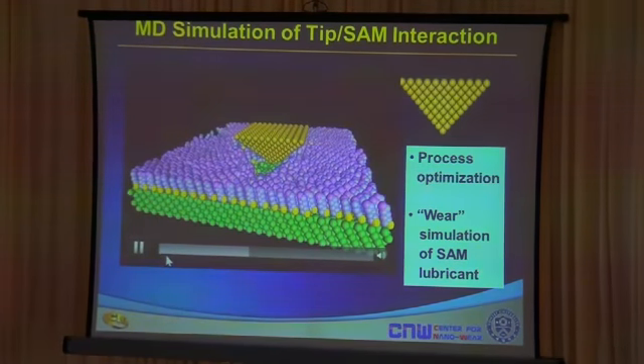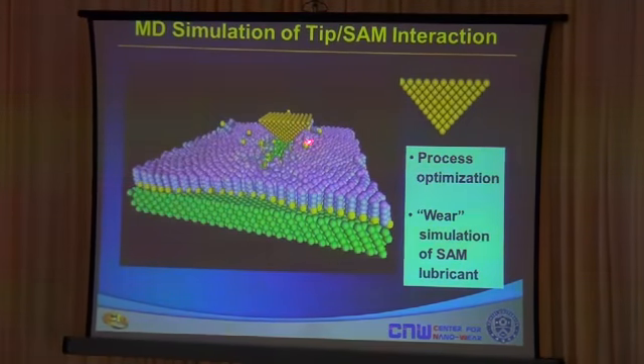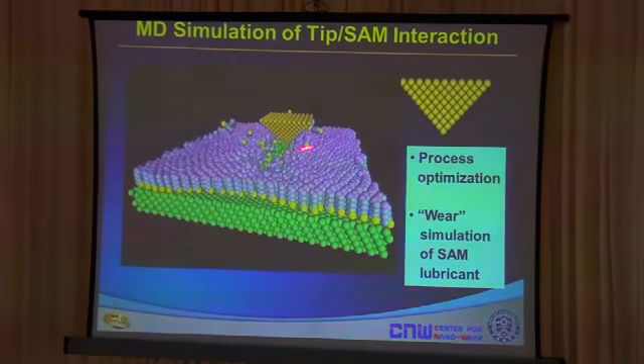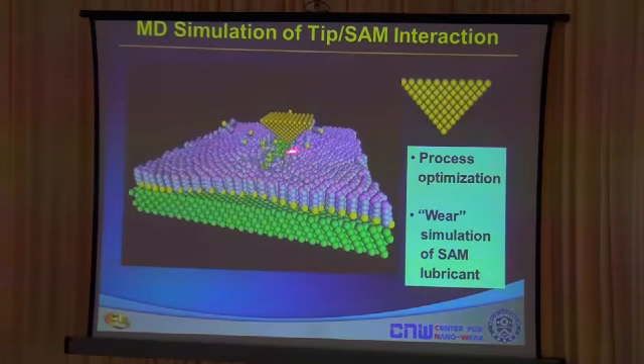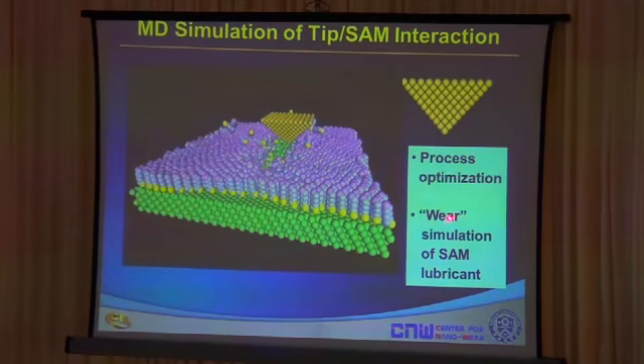In order to see the effect of the tip size, we performed molecular dynamics simulation where we scribe the surface using a very sharp tip, and we can look at the width of this pattern, and this will be the theoretical limit of this particular process. What we see here is that the width is actually wider than the tip because of the van der Waals force between the molecules. As these molecules are moved mechanically, they pull the surrounding molecules by van der Waals force. So the width of the pattern has to be inevitably slightly larger than the tip width itself.